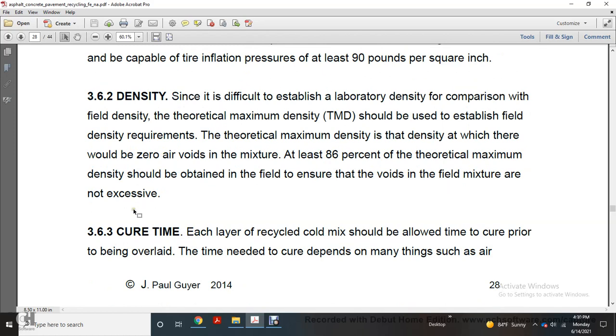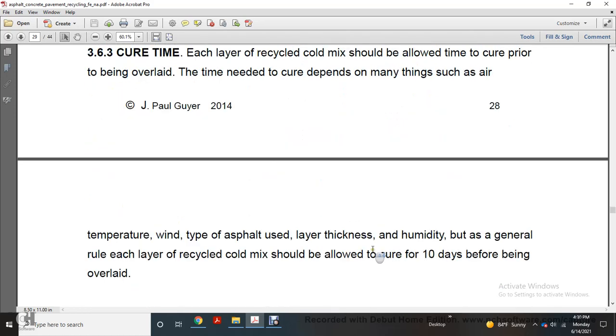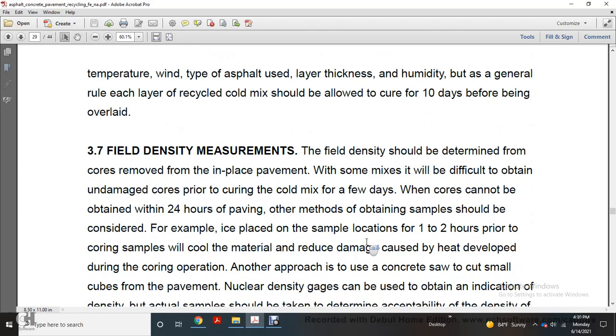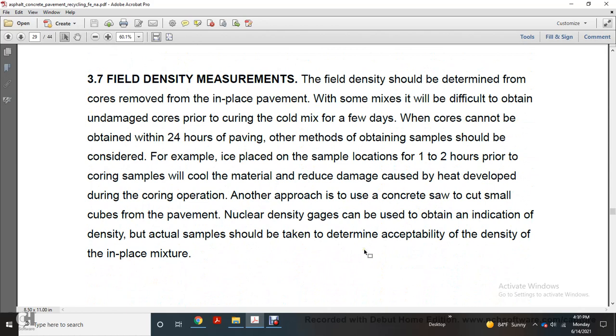Alright, 3.6.3, cure time. Each layer of the recycled cold mix should be allowed time to cure prior to the overlay. The time depends on such things as air temperature, wind, type of asphalt, layer thickness, and humidity. As a general rule, each layer of the recycled cold mix should be allowed to cure for 10 days before being overlaid. Field density measure.